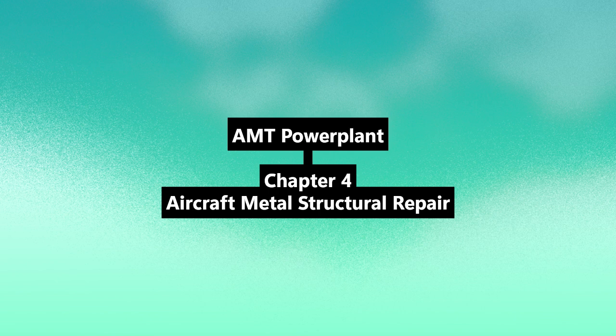Interestingly, the source warns against making a repair too strong. Really? How can it be too strong? If it's significantly stronger or stiffer than the surrounding structure, it can cause excessive flexing and stress right at the edges of the repair. It can actually lead to fatigue cracking around the super strong patch. Balance is key. Okay. Maintaining original contour, that's about aerodynamics. Precisely. Keeping the original shape and smoothness is crucial for performance, stability, fuel efficiency. Repairs need to blend seamlessly. No bulges, depressions, sharp edges disrupting airflow.